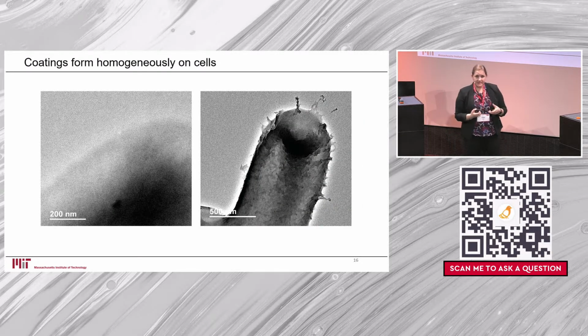We can also look at cells coated in these and see that there's a very uniform coating. So this technique is called TEM, and basically it looks for metal ions. So normally you have to stain cells to get resolution. On the left here, you see an unstained cell that's not coated. It's very fuzzy. On the right, we can actually use the metal ions in our coatings as the imaging agent. So we can see this very consistent coating with very high resolution.